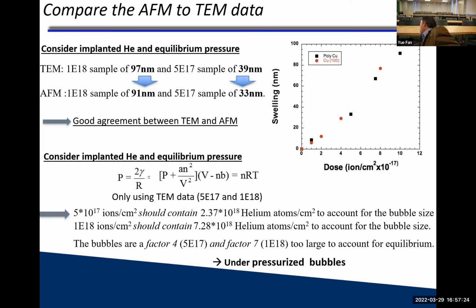And so to account for the bubble size, if the bubbles would be in equilibrium, the same is true for 1 × 10 to the 18, which should contain this much helium. So that means our bubbles are under pressurized. They actually have a lower pressure than they can accommodate. Well, why is this? Because at the same time we're pumping in all the helium, we're also pumping in 50 dpa of displacement damage, and we create a lot of vacancies and interstitials at that point. And so a lot of that cavity space is actually attributed to the vacancies rather than just the helium itself.